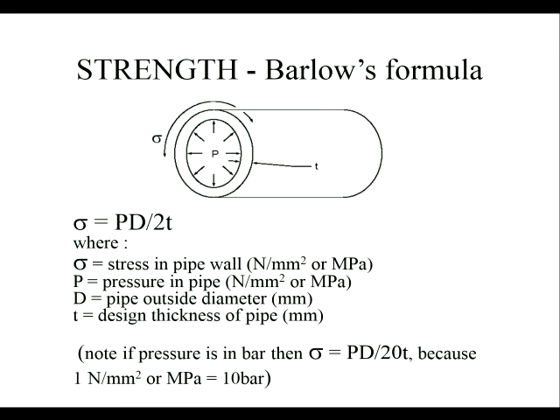Now why is this important? Well, because the basic calculation that we do about strength in a pressurised pipe comes from Barlow's formula. So if you imagine a pipe, you can see here, of diameter D and wall thickness T, and the assumption in this equation is that the pipe diameter is very much greater than the wall thickness. Then the stress in the pipe wall is the pressure times the diameter divided by 2 times the wall thickness.